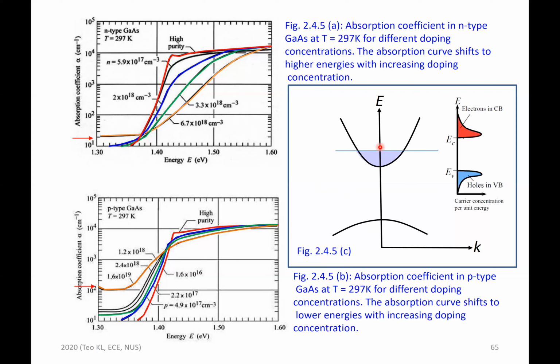So then you expect the absorption coefficient to decrease. You can take any value, let's say at 1.43 eV. Okay, if you draw a vertical line, you can see that the absorption coefficient drops from the high purity, which is no doping concentration, to high doping concentration. The absorption coefficient actually drops in value for a particular photon energy as you increase the carrier concentration.